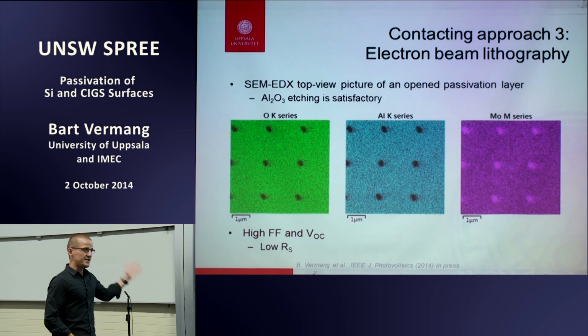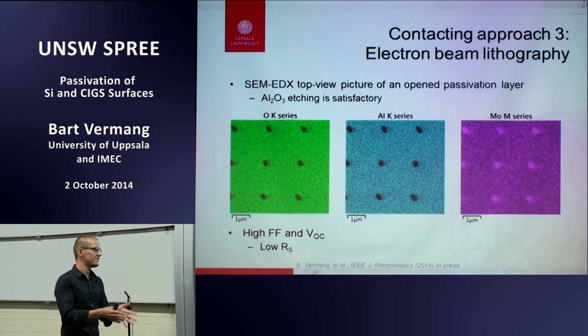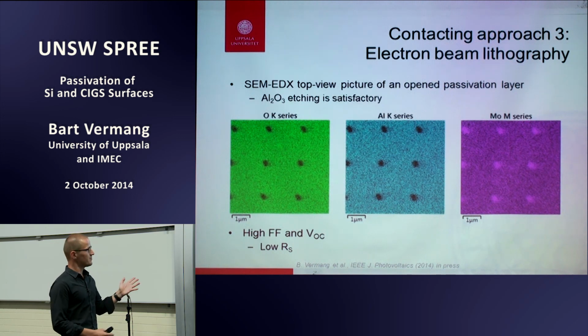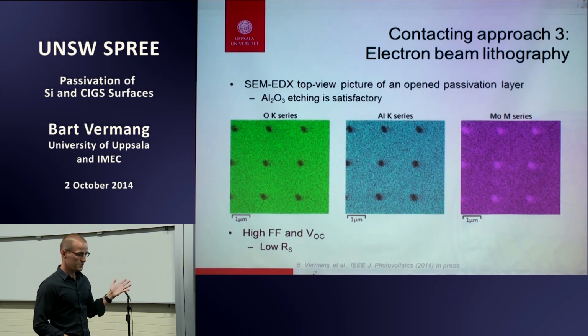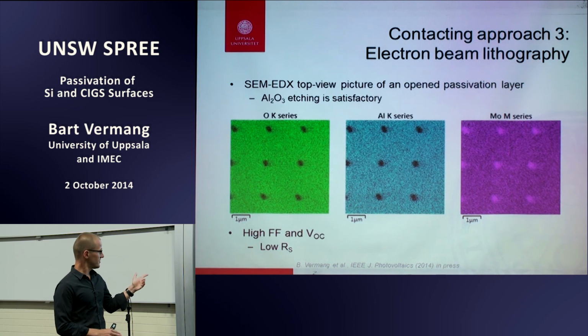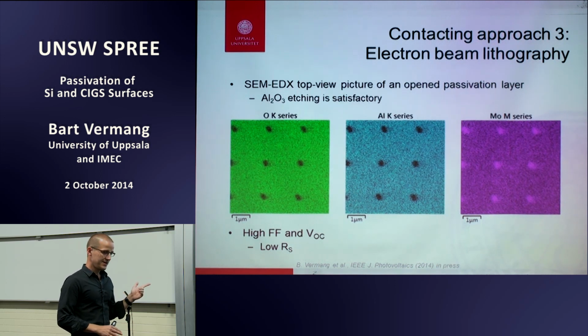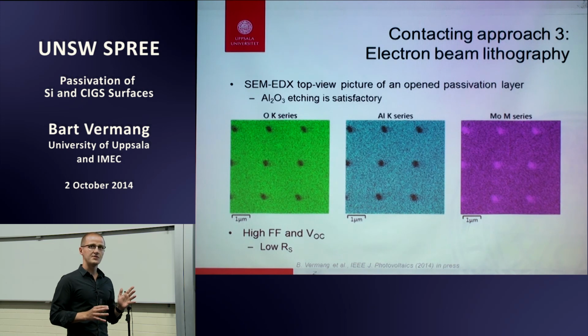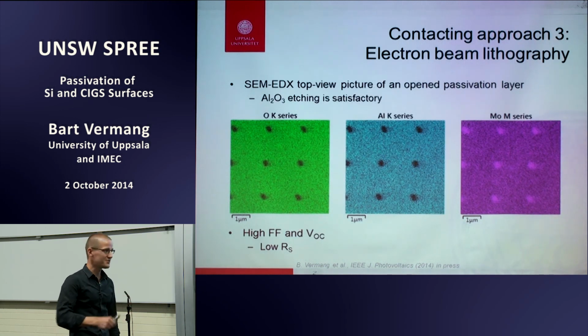We are making SEM pictures, STEM pictures as much as possible to really see what's going on and how it looks. And at least we see the openings, we see the passivation layer, so that's very positive. But of course, we are still looking at a very small area compared to the full area. But we're quite confident. For example, one of the things we did in the beginning was comparing, in the first paper, Solar Energy Materials. We were still using 2 thin aluminum oxide layers, and we could not see them in SEM. And even in TEM, we had difficulties because it was just one peak, just one measurement was the aluminum oxide layer, so it was not conclusive.